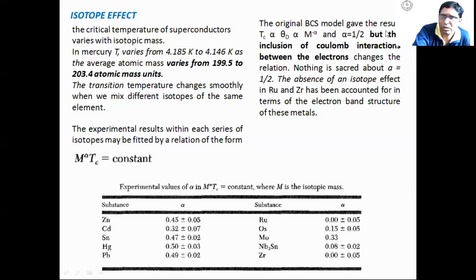Okay, and the BCS theory also gives the result that Tc is proportional to theta D. Theta D is the Debye temperature, which is proportional to m raised to power minus alpha, and alpha is equal to 1 by 2. But if you consider the Coulomb interaction between the electrons, then the value of alpha changes. So alpha is not necessarily 1/2, but in many cases it comes out to be 1/2. But it is sure that the elemental mass plays a role in deciding the critical temperature. The isotope effect is a very important effect that people have studied, the variation of critical temperature with isotopic mass.